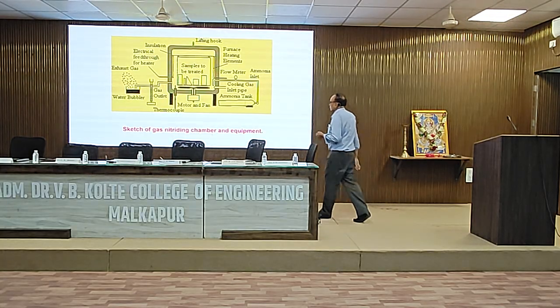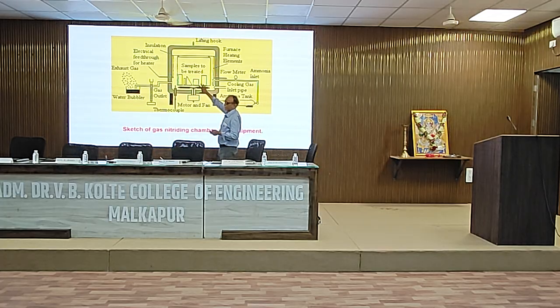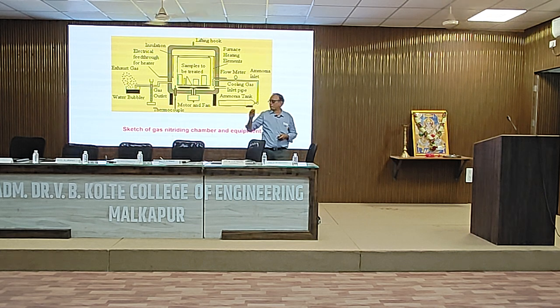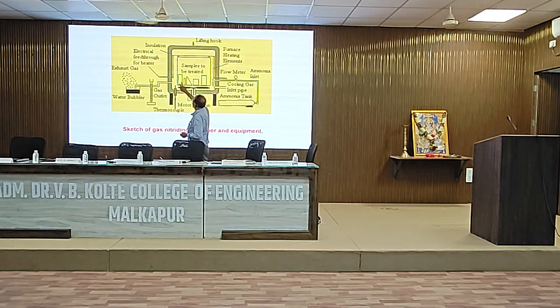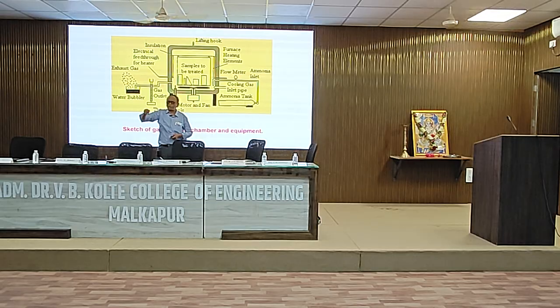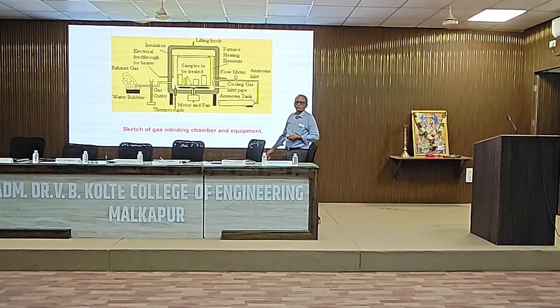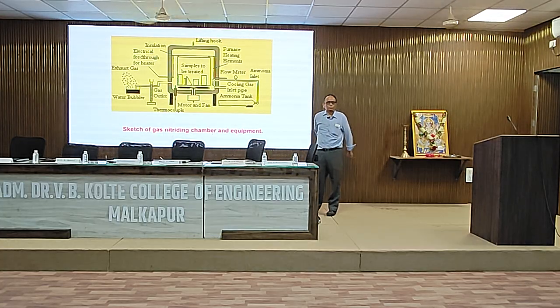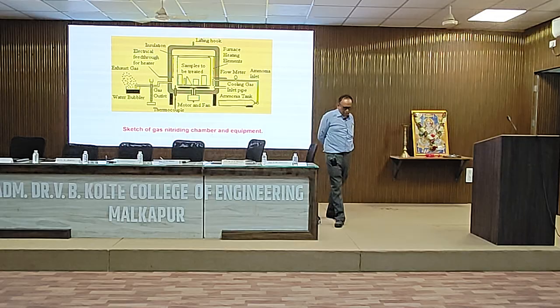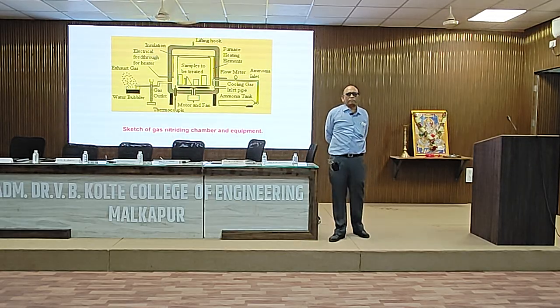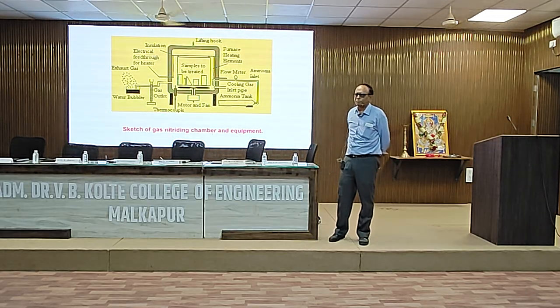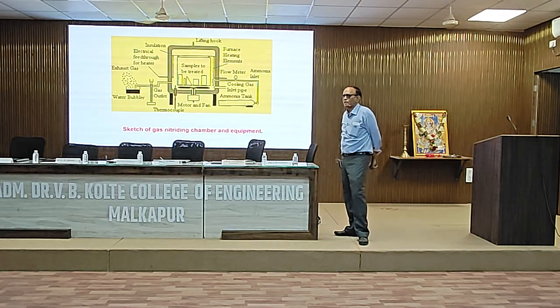So basically, in gas nitriding, you have the components kept in the chamber. The chamber is heated to around 500-600 degrees centigrade, and when you feed your ammonia, it undergoes catalytic decomposition. All these nitrided cases are formed onto the component surface. Remaining ammonia is bubbled through the water and dissolved into the water, and you get the nitrided case onto the sample surface. Now, here, by default, you get a mixture of epsilon phase and gamma prime phase, Fe2-3N and Fe4N.